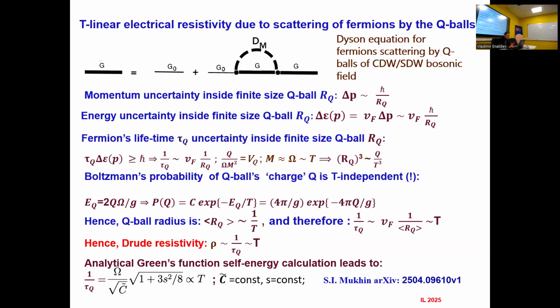Next, I should probably be brief, but in principle, you could consider electrons which are not in Q-balls, which are outside Q-balls, so they're in the normal state. And there are Cooper pairs which are inside the Q-ball. So electrons may be scattered by this deformation of the Q-ball amplitude field. This spin or charge density wave local fluctuation, which is a Q-ball, they would be scattered by it. And if you calculate such a diagram, you can find out what is the lifetime of normal, not paired fermions, scattered by Q-balls, which are considered then as impurities, but with temperature-dependent amplitudes.